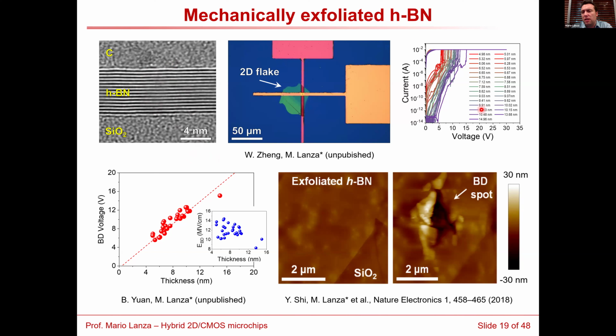We measure many, many devices with many different thicknesses, and we observe something very similar. Low leakage current that, of course, increases for thinner samples. We show a dielectric breakdown. The electrical field is almost constant, around 12 megavolts per centimeter. Its breakdown voltage follows a trend. However, in this material, because it has no defects, when we trigger the dielectric breakdown, it's a very hard process and it completely breaks the device.